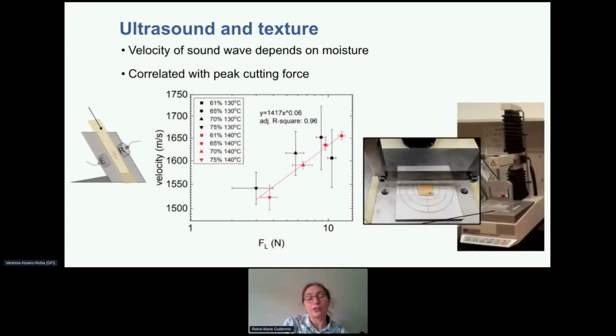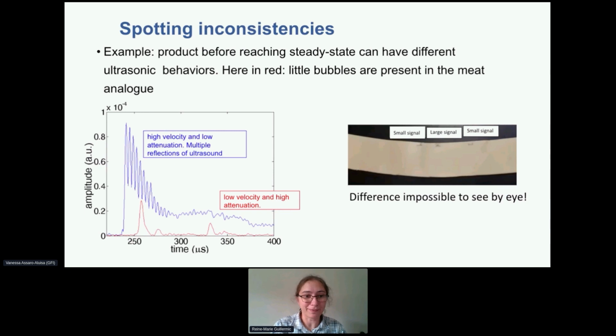The result we obtained that is interesting is that you have a correlation between velocity and force. They vary the same way, so you can really correlate the velocity that you get in your material, the ultrasonic signal, and the force. So it's very good because it's really a potential tool to see if the material has basically the softness that you desire, for example. You can go forward.